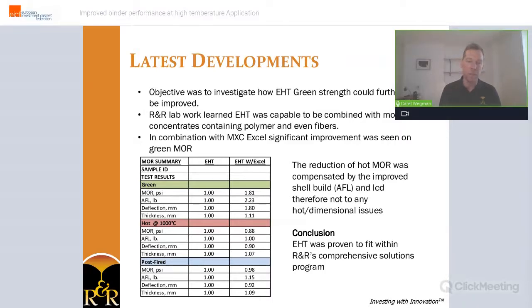From the normalized data, you can clearly see that the additional polymer makes a significant improvement to the green strength. It did, however, reduce the hot MOR, but it's not considered an issue, as the additional shell build equalizes the AFL figures. So nevertheless, what we can conclude from this research is that EHT is capable of fitting within R&R's comprehensive solutions program. Its performance can be adjusted to resolve specific issues in any foundry.